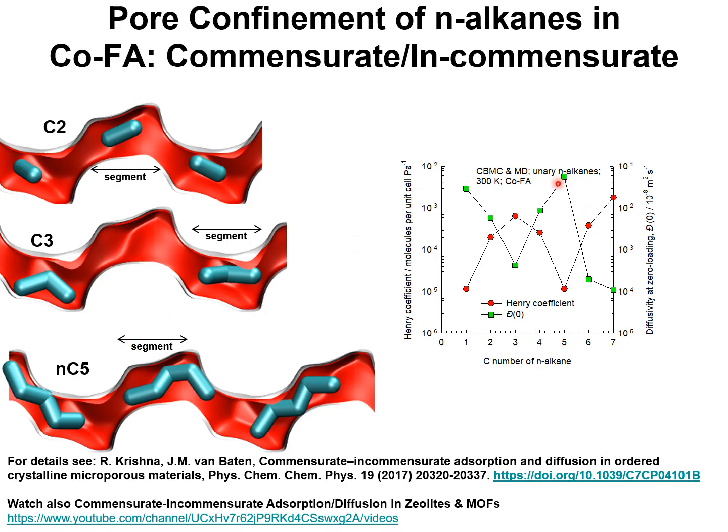Normal pentane has a length that is longer, and the length of a normal pentane molecule is larger than that of a single segment. So NC5 is incommensurate with respect to the length of one segment. That explains the higher diffusivity of NC5 with respect to propane.